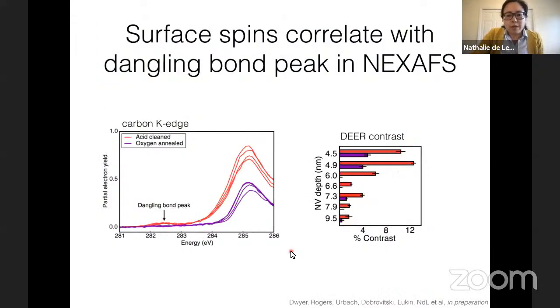Okay, so now what we'd like to do is go into the X-ray spectroscopy and the surface spectroscopy to figure out whether we see any feature that correlates with this DEER signal, to see if we can figure out what gives rise to these surface spins. What we find is that if we look at the carbon K edge in NEXAFS and zoom in on this little region here, there's a tiny peak that shows up around 282.5 eV. That's in samples where we have a lot of DEER contrast, or a high DEER signal, and it's gone in samples where we see lower DEER signal.